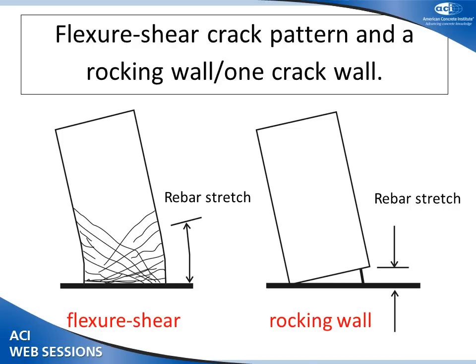What we're expecting from all of our studies and from good, well-detailed walls in the field is a spread fan pattern of cracking, flexure-shear cracks, which distributes the stretch of the rebar up a reasonable height of the wall. What we are actually getting, and have seen in numerous buildings, I've personally seen 4, and I know of at least another 5 in Christchurch, is that the walls, though they're designed for flexural yielding, actually only split at one crack, typically the construction joint above the beam or the foundation. And all the bar stretch was concentrated in that one crack.